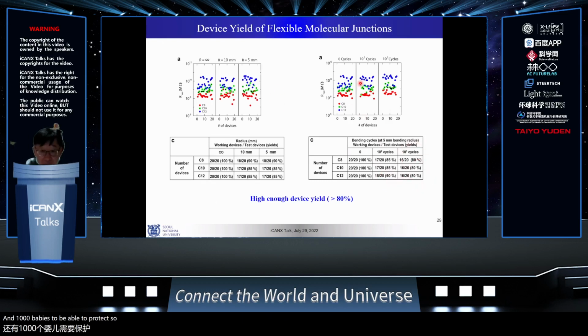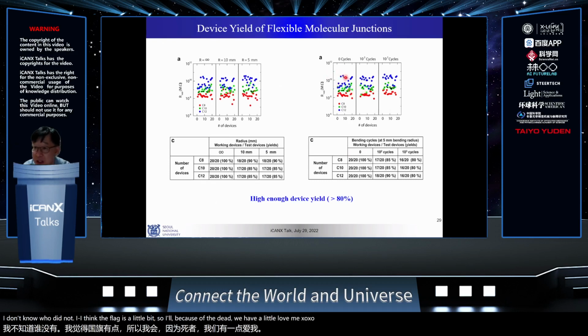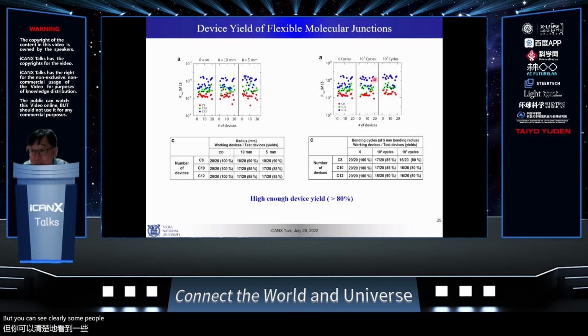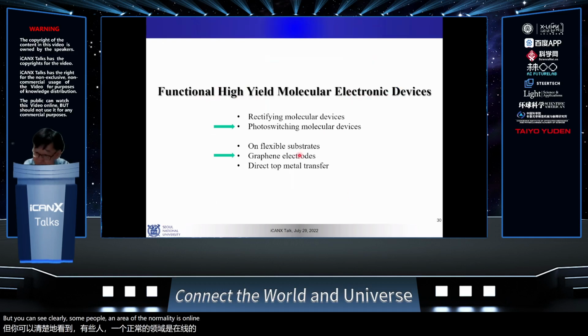There is a little bit of current distribution. That distribution is due to the flatness of the bottom surface. The bottom gold is not atomically flat; it has a little roughness, and because of that we have a little spread in the current. But you can clearly see the different areas of the long molecule, middle molecule, and short molecule. The yield is 80%. So now we have a high-yield approach.